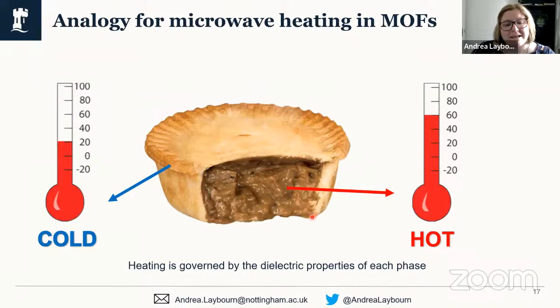And so what we can think of in the case of our metal organic framework reactions is that our linkers are acting as the pastry, so will stay cool, whereas our solvated metal salts will get hot in the microwave field. From this information, our knowledge of the underpinning mechanisms and the dielectric properties measurements, we hypothesized that you would have a selective heating mechanism, where you're heating the metal ions in solution over the linkers for the synthesis of metal organic frameworks.